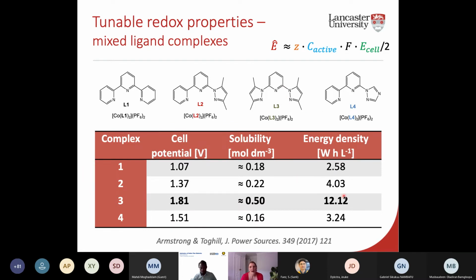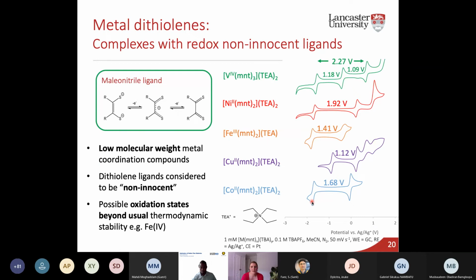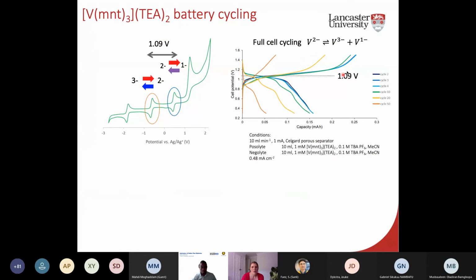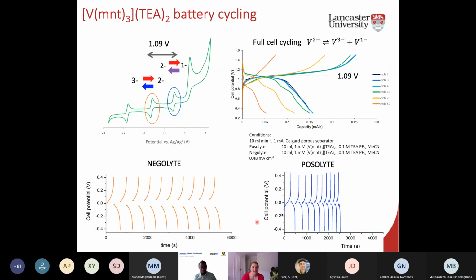And that looks really good in terms of the voltammetry and then the outcome and the solubility. But then when you in practice try and put it into a flow cell, you'll find that you've got unstable species when you're being charged. And this is the case, we made these complexes here with maleonitrile ligand. They all look great on cyclic voltammetry, but when you put them in full cell cycling, we get a massive decay. So what we've started to do in the group is explore the stability and the lifetime of these species when they're in negative or positive state.